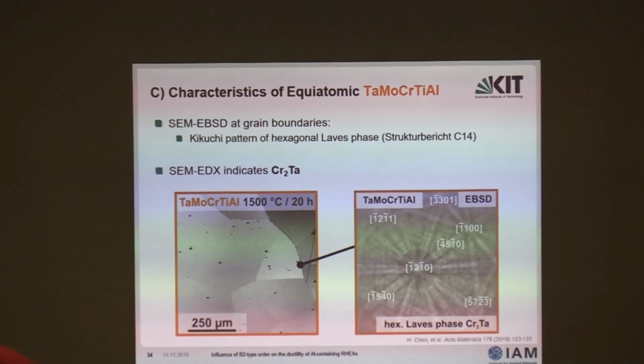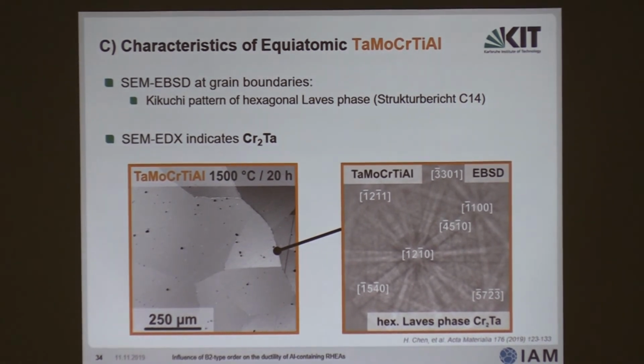So we then tried, and this has been published in the paper which we have recently done in Acta Materialia, another paper from this year. Let me see, I need to go a little bit forward again. This one here. In 2019, this has been published in Acta Materialia. With high-resolution transmission electron microscopy, you can get an idea about which atom sits on which lattice site, but it's still hard. And it's also hard with atom probe tomography. Probably we would need help from DFT guys in this matter.